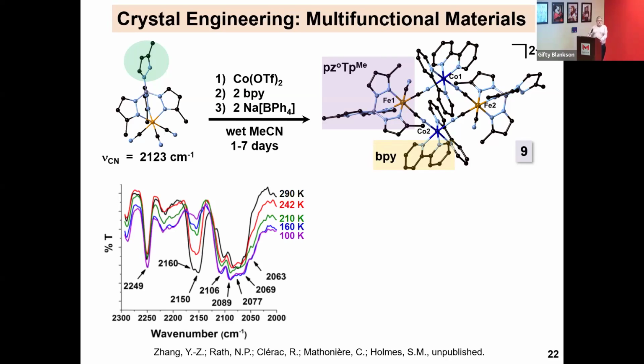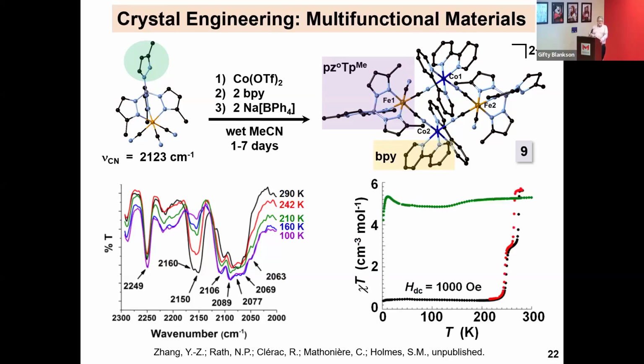And so you see big changes in the infrared spectra. Because we had lattice acetonitrile, methyl cyanide, or solvent, that's this absorption here. It doesn't participate in electron transfer, so it stays put. It doesn't change when we change the state. But the cyanides involved in the bonding between the cobalts and the irons and the terminal cyanide change their energies a lot, again consistent with that intramolecular electron transfer.